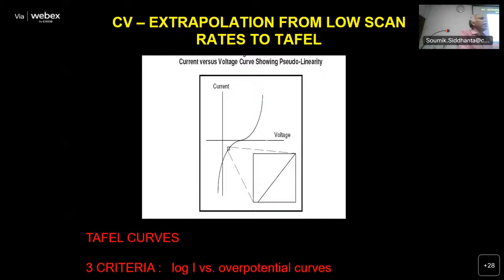The second criterion is at least one order of magnitude of linearity, because you are plotting log current: 1 to 10, 10 to 100, 100 to 1000. This is a semi-log plot, eta versus log I. The third criterion is that you should be away from the mass transfer limit. If you know the limiting current, stop at 1/10 of the limiting current, so that you are in the logarithmic region. These three criteria can be used to get a good, reliable Tafel slope. Theoretically the Tafel slope is 2.303 RT/nF: 60 millivolts, 30 millivolts, 120 millivolts, 90 millivolts, that's all.